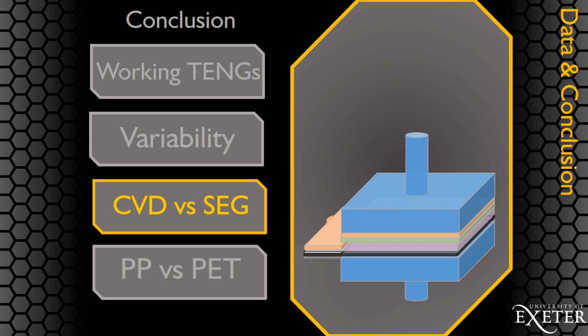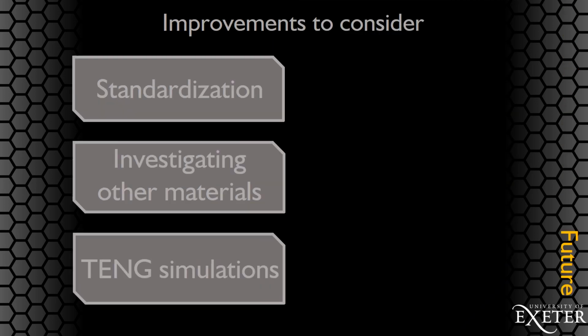CVD didn't perform as well as expected due to unpredictability and high accuracy needed to achieve working samples. For this, SEG appears to be the preferred graphene type as it's less energy intensive and more scalable. The PET substrate gave more reliable results owing to its better adhesion and greater applicable range, but PP fibers still show promise as the first steps toward textile integrated TENGs. Next time, a standardization procedure should be made that guarantees improved TENG performance.